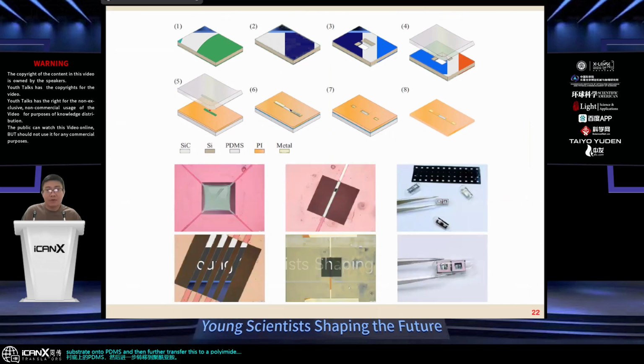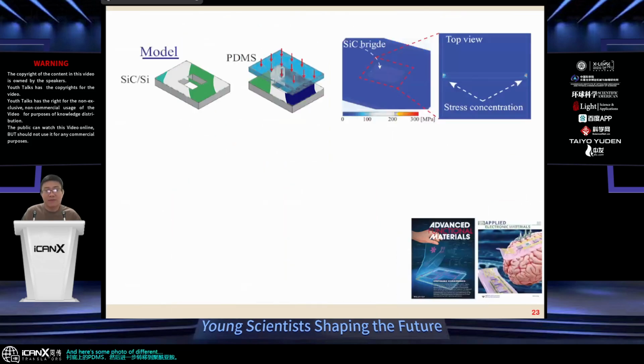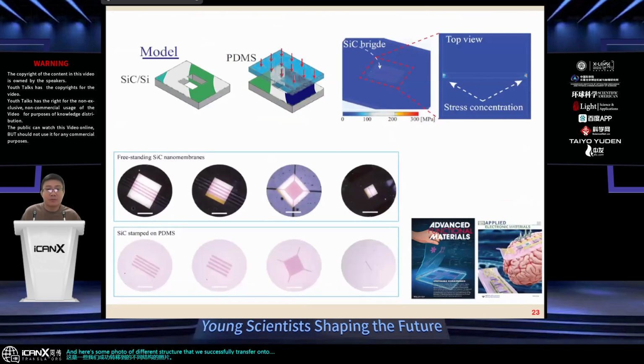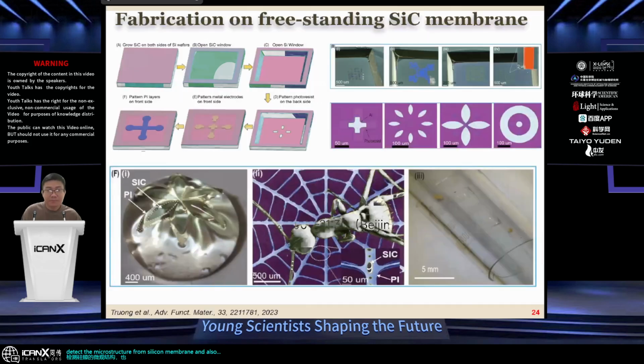And here are some photos of the different structures that we successfully transferred onto PDMS and then polyimide. Under simulation, we also found that the cracks concentrate at the anchor of the microstructure, able to beautifully detach the microstructure from the silicon membrane and onto PDMS.